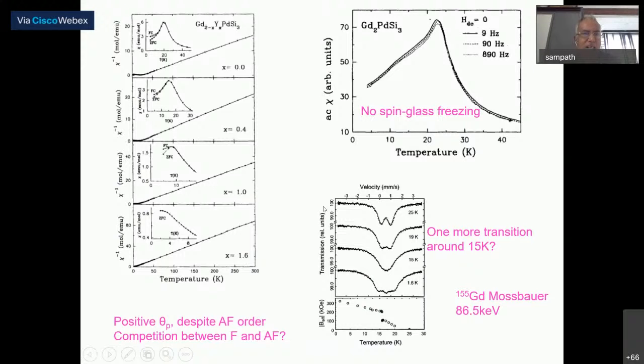Now, since I decided to stick to Gd2PdSi3 to a large extent, I will briefly show the data here. This is susceptibility as a function of temperature. This inverse susceptibility is essentially linear, Curie-Weiss behavior, where theta p is positive. If theta p is positive, that implies there is a strong ferromagnetic correlation. Our system undergoes antiferromagnetic ordering at low temperature. Sorry, my cursor is not working well. Antiferromagnetic ordering here at something like 21 Kelvin. So we also did Mössbauer spectroscopy in Berlin.